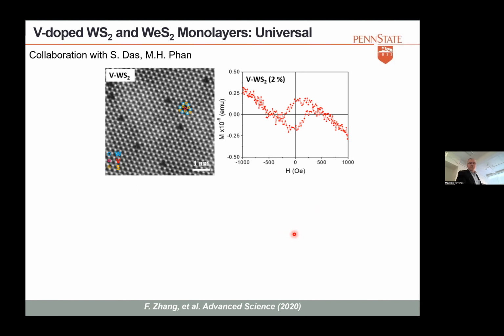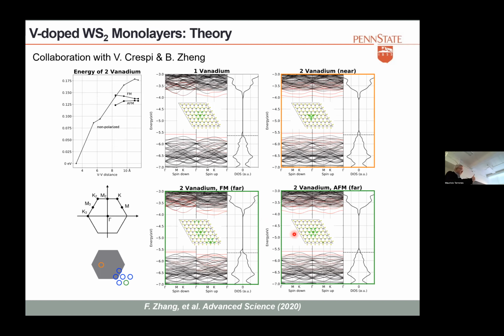But again, I think we need to do more measurements. One possibility depends on how far apart you have the vanadium atoms. When you do spin polarized density of states, if you have the vanadium atoms apart by 1 or 2 nanometers, you can align the spins. When you apply a magnetic field, in principle, you can magnetize them. But when they become closer to each other, you have an antiferromagnetic contribution. So when they are very close, they cluster, and all this ferromagnetic contribution goes away, and when they are farther apart, you have this spin polarization. So this could be a model for this, but again, we are trying to do some optical measurements